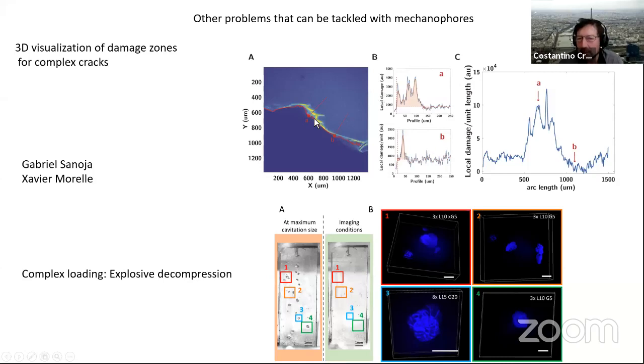Here A and B correspond to profiles starting from the crack face towards the interior. You can see how the intensity fluctuates. This can be integrated point by point along the arc, and then you can have a local damage per unit length as a function of arc length. So you can see that indeed, as the crack propagates in a tougher material with more complex propagation conditions, it is something that varies spatially and temporally. So the crack is not necessarily moving in a well-behaved way. I'm not saying we can predict it, but we can certainly see it and characterize it.